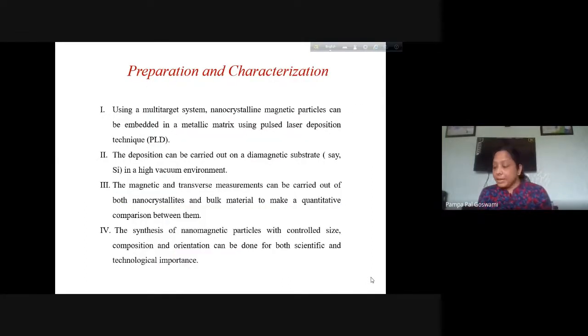And after preparing, we have to characterize it. So how can we characterize it? First of all, I want to say that these alloy systems were prepared by the arc melting process under argon atmosphere. After preparing these alloy systems, we have to make thin films of these systems. So nanocrystalline particles like NiMn and NiFeCr can be embedded in a matrix using the pulsed laser deposition technique.